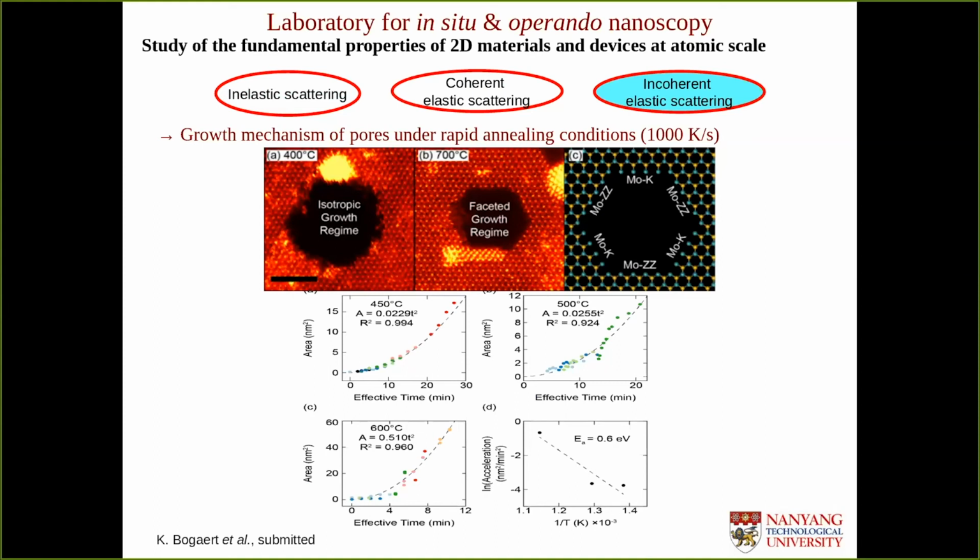And the last slide, if I may, is high temperature measurement at atomic resolution inside the TEM. It's also on MoS2. We follow the growth of the facets inside the TEM at different temperatures. And we have been able to see that depending on the temperature we used, we have different edge reconstructions, and we can also estimate the growth rate of the pores and the growth rate of each of the edges by studying quite a variety of samples.